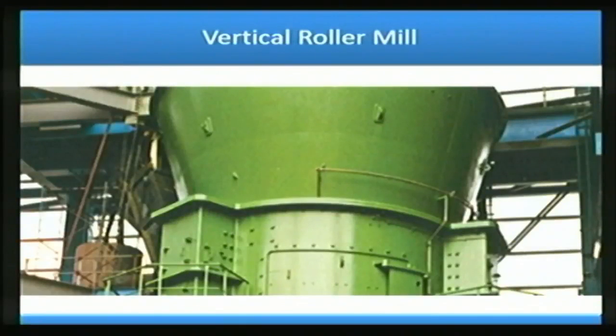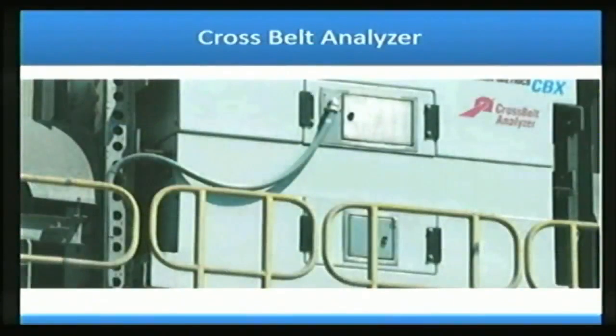And one of the major challenges is how to control the particle size distribution as far as the grinding of cement is concerned. So we have various combinations at the plant manufacturing stage itself. There is a combination of ball mill and roller press, and you have VRM as well as roller press finish. So you can have permutations and combinations of various grinding media and grinding aids, so that, not being confined to fineness of cement, we also look at the particle size distribution, which is very critical. So we are able to bring that out.